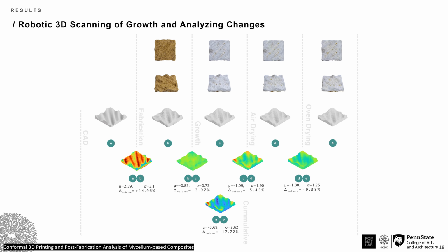These reconstructed geometries were then compared against both the digital model and each other to determine the difference in geometry between stages. Using a signed distance approach, we were able to quantify these changes using descriptive statistics. The materialization error captured by the comparison between the AB pair presented significant overextrusion along the valleys. We believe this is primarily caused by the material spring back, where we observed the extruded material to expand slightly after deposition. Similarly, we observed a loss of geometric fidelity around the edges, likely due to the limitations of large-scale 3D printing.